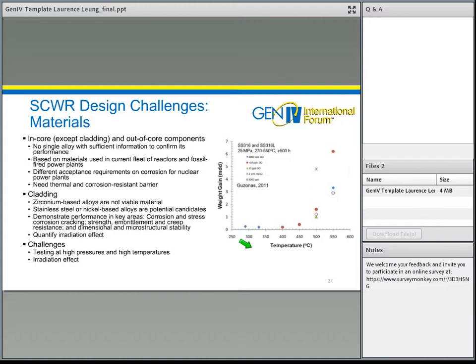But keep in mind that in many cases, the cladding stays in the core for a very short time, and every year we take it out and move the fuel into a different location. After three batches, we take it out from the core. On top of that, we need to quantify the irradiation effect on these key technology areas. So this figure shows an example of the measured weight gain for stainless steel 316 and 316L at the supercritical SCWR condition.